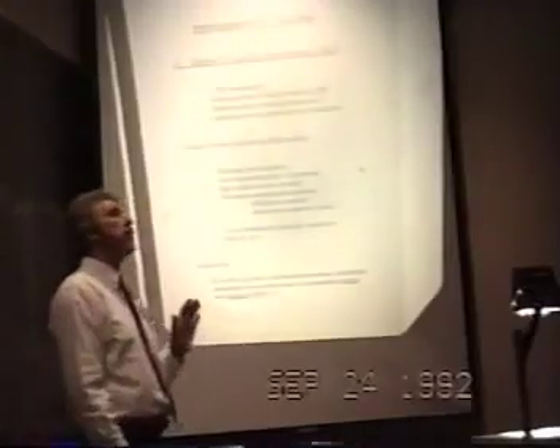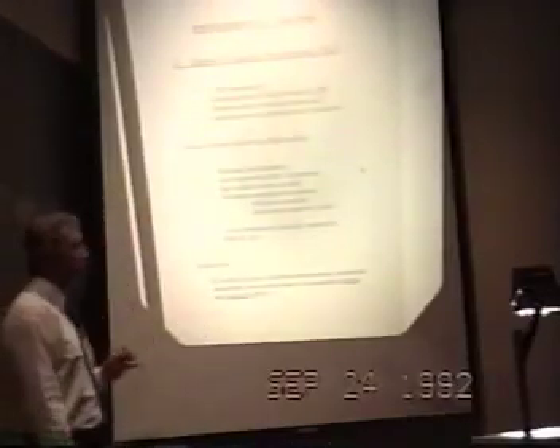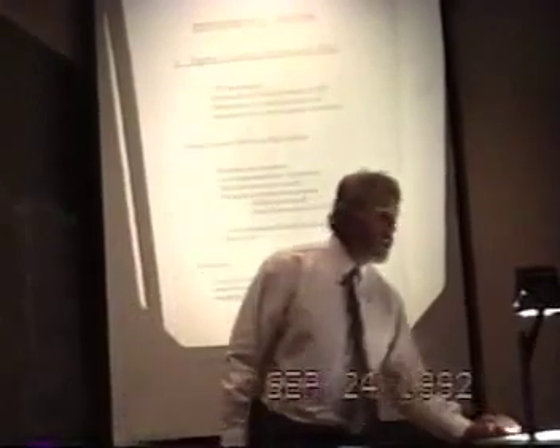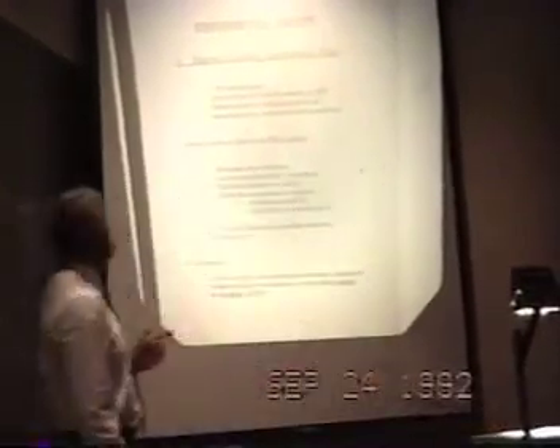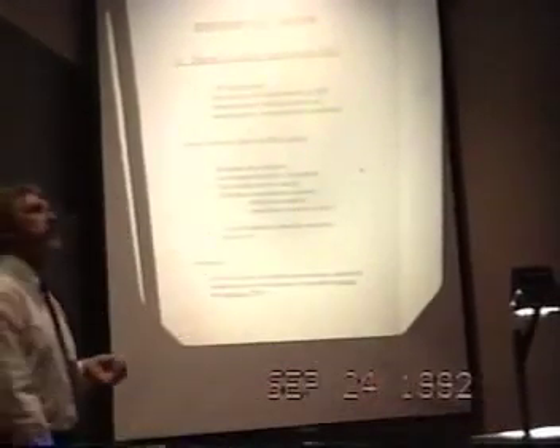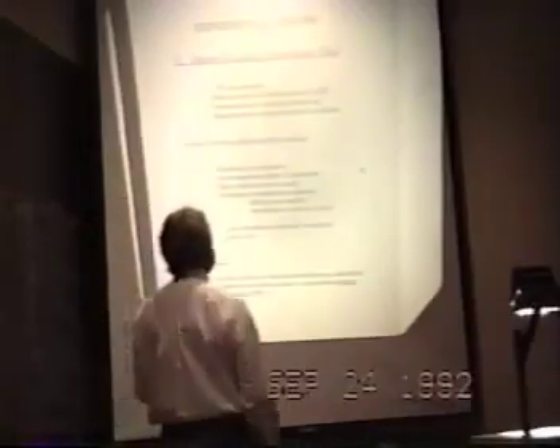Our experiments were divided into 3 groups, and I'm really going to concentrate on the heat results today. But in order to obtain excess heat in these experiments in our hands, one must achieve deuterium to palladium loading ratios in excess of a value of something like 0.9.